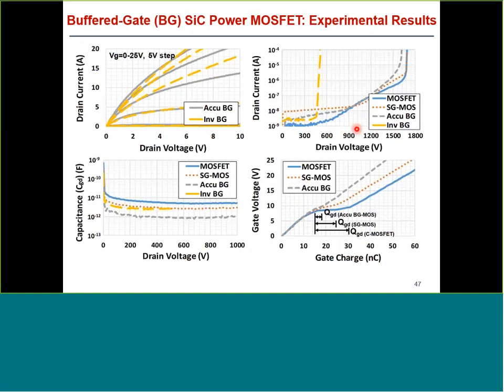In terms of breakdown voltage, we get very good breakdown voltage for the conventional MOSFET, the blue line, the SG MOSFET, and of course the accumulation mode BG MOSFET. However, we found that our inversion mode BG MOSFETs had poor breakdown voltage of about 500 to 600 volts. We did a lot of investigation into the cause of this, and it has to do with the particular implant profiles. You can find this discussion in one of our published papers.